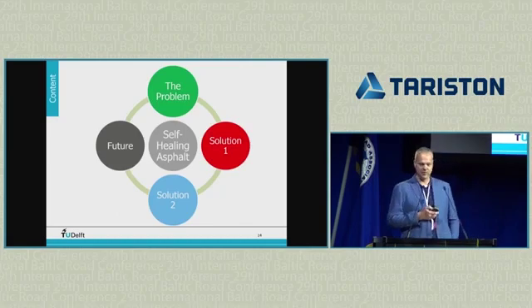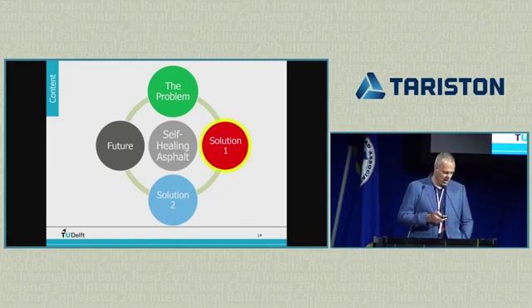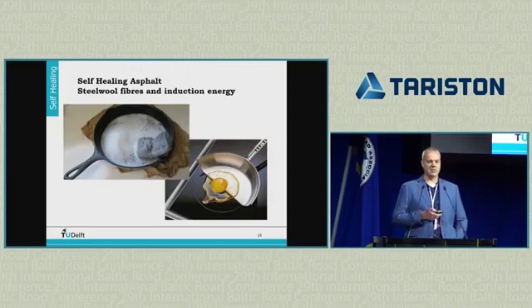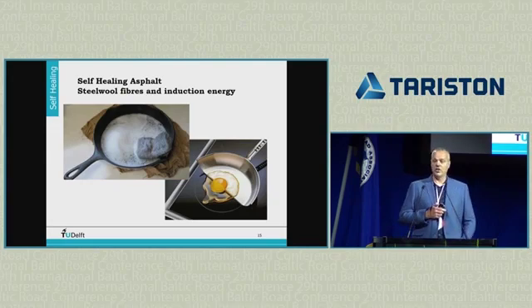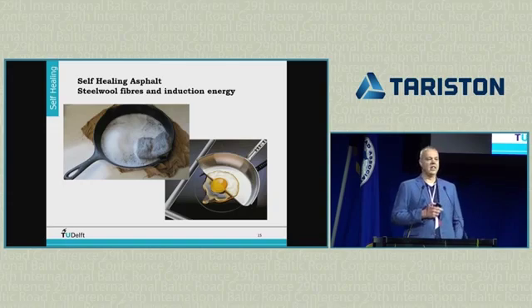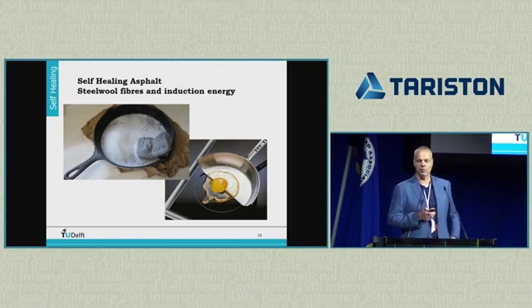So what is the solution to overcome this? The first solution that we came up with is very simple. You have to use tools from the kitchen. What we do is we use steel wool, these steel wool pads that you use to clean pans. We cut them in small pieces and mix them through the asphalt. Then we use induction energy, an induction coil, to actually heat up the steel wool. The induction coil is similar to the thing you use for cooking. You hold the induction coil a little bit above the surface and heat up the steel wool.